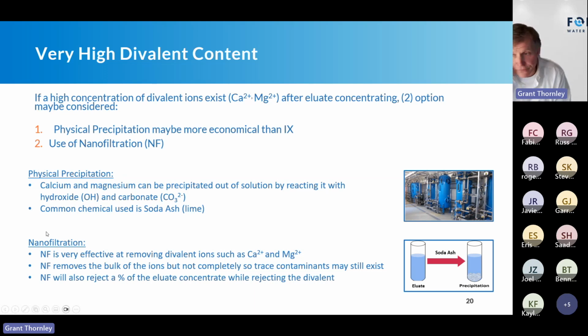Nanofiltration, you may find that in the DLE process flow sheet. It's very effective at removing divalent ions. It's great. However, it doesn't remove 100% of the calcium and magnesium. There's going to be a little bit of trace. If it was a sulfate, just so you know, a large molecule, it's going to reject everything. But calcium and magnesium, it does a great job of removing the bulk, but you're still going to have some trace contaminants. So that will be addressed through the polishing.